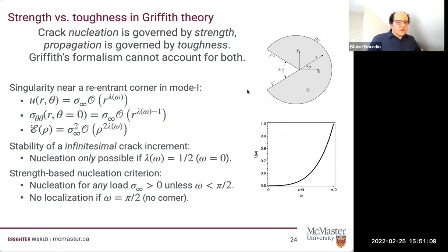I can quickly describe the incompatibility between these two concepts by looking at classical elliptic regularity issues. What you'll see is something you can find in any good book on the topic. Look at a domain with a reentrant corner like that, and assume it's loaded in mode 1, so you stretch something that has a V reentrant corner. You can show that if you do a blow up near the crack tip, the displacement in polar coordinates will be of the form sigma infinity, that's the applied load, plus some r to the power lambda, which depends on omega. You can compute this lambda as a function of omega. That's this curve. It goes from 1/2 when omega equals 0, that's a crack, to 1 when omega equals pi/2, that is, you just have a flat interface.